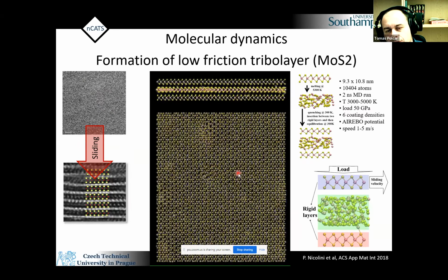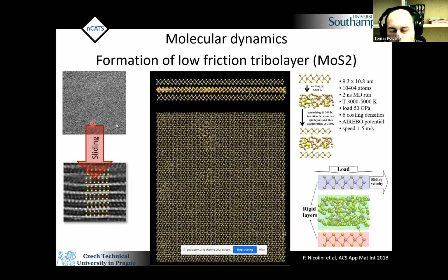I would be a little bit careful here to say that it's one-to-one, because of course you see that we have only three layers, while here we have really relatively thick material. And the conditions we had to use in order to simulate the model a little bit were quite extreme: extremely high load and extremely high temperature. But actually, and when I say we, it was mostly Paolo Nicolini, who was my postdoc at that time, developed quite a nice way to look at what more we can get from the simulation.